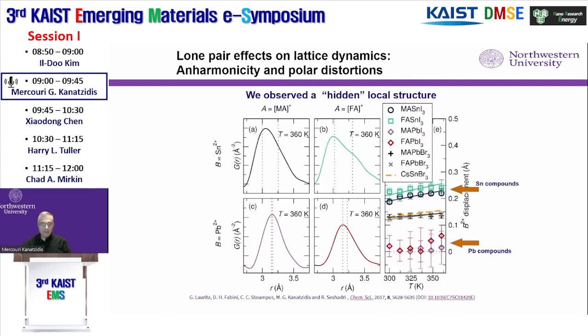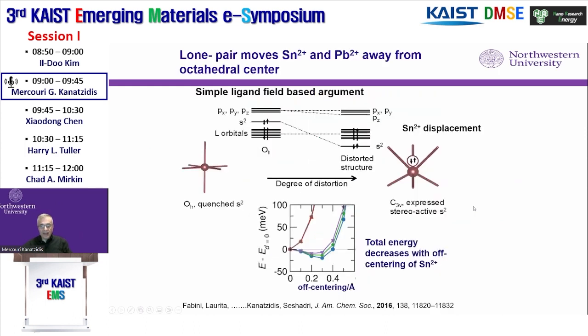How do we know this is happening? We figured this out using pair distribution function analysis, X-ray scattering, with Ram Seshadri, and we found that in order to best fit the data, you have to move the atoms off-center with respect to the octahedron. So the tin actually has the most displacement, and the lead has less displacement than the tin. Another thing we found is that when you heat the samples up, the displacement becomes bigger. So at higher temperatures, the displacement becomes more off-center. This is also shown here in a different form.